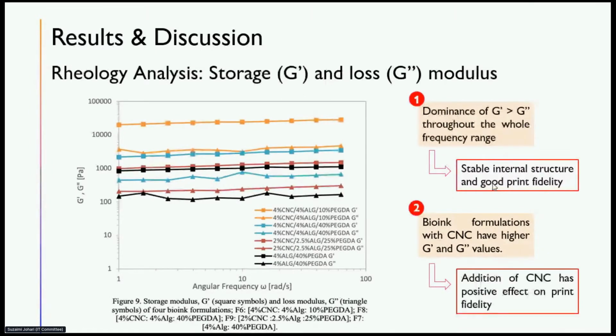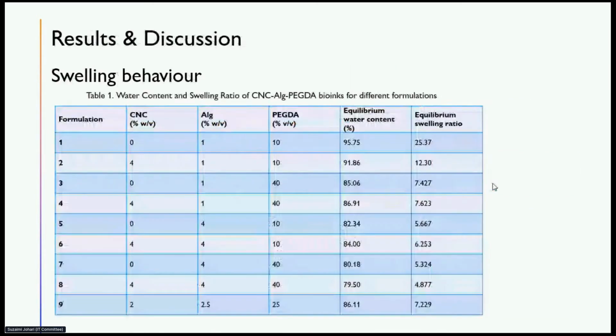The data show that the bioink formulations with CNC, which are the orange, the blue, and the red ones, have higher storage and loss modulus values compared to the bioink formulations without CNC, which is the black flow curve. This shows that the addition of CNC does have a positive effect on the print fidelity. Next slide.